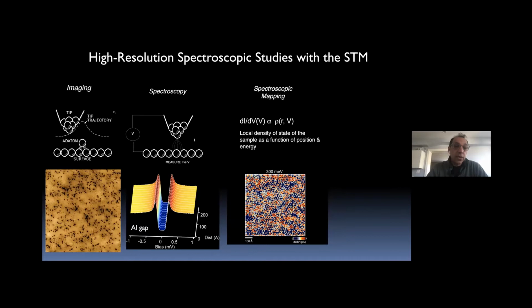As you know, my group does scanning tunneling microscopy, and over the years we do imaging and, of course, local spectroscopy, where you measure the local density of states with a high energy resolution, and you can do spectroscopic mapping to map out how the density of states looks in real space.